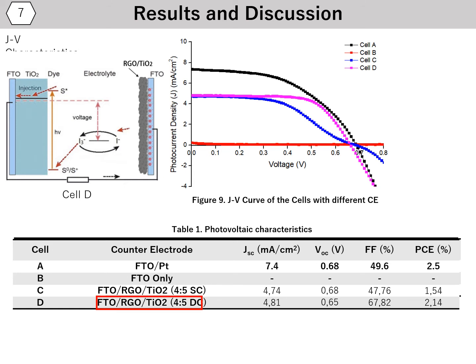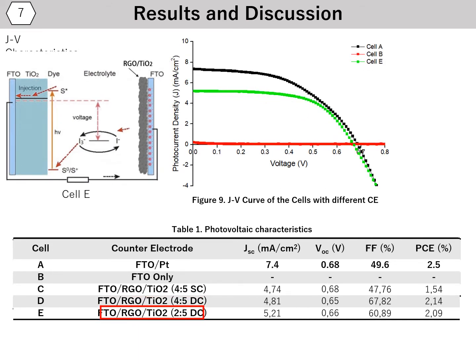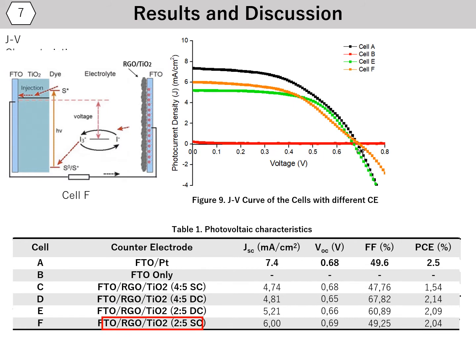To see the effect of amount of RGO, we compare with different ratio of RGO and titanium dioxide of 2 to 5 in weight. The cell with the RGO TiO2 nanocomposite in film using drop casting deposition shows slightly higher current density value than cell C and D. Cell F, using spin coating deposition, possesses higher current density value than cell E. This indicates that a lower amount of RGO in RGO titanium dioxide may improve catalytic properties of counter electrode, since lower resistance of RGO in ratio 2 to 5 than 4 to 5. With lower thickness, it may provide sufficient area for reduction of iodide triiodide ion and affect higher JSC value than cell E.